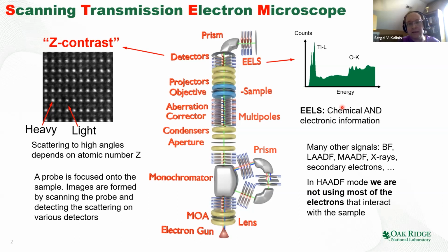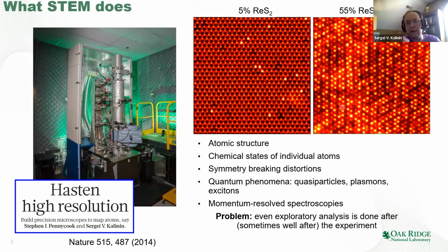The thing that is really astounding is that the energy detection limit of the electron microscope now is 5 to 7 milli-electron volt, where the beam energy is of the order of 50 kilo electron volt. So this is absolutely amazing because you use the electron beam at tens of kilovolt energies to detect the quasiparticles, which are 5 milli-electron volt. It's not quite approaching the level of STM, but is getting very, very close.